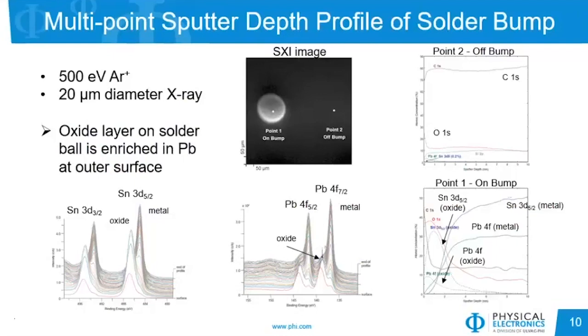And going from the front of the figure toward the back, we are going from the surface to the bulk of the material. And for both the tin and the lead that comprise this solder bump, we see at the beginning there is an oxide layer, and as we sputter deeper into it with the argon, we do see a metal as expected. The figure on the bottom right shows us an overall depth profile of this solder ball, and we can see that there is the oxide chemistry and the metal chemistry of both the tin and the lead that we can separate out using curve fitting and LLS, and we can even see that the lead is preferentially enhanced at the top of that oxide relative to the tin. And so that is an example where we can use the monoatomic argon for sputtering of this material.